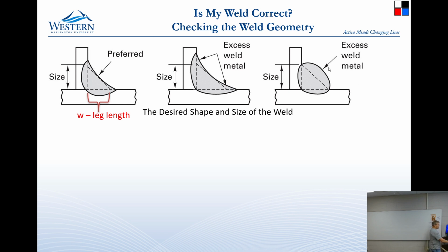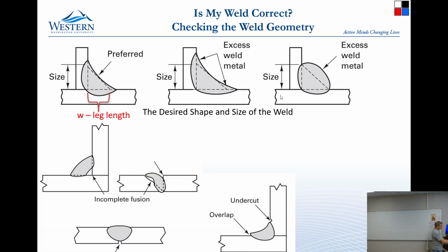If you happen to have excess weld material and it's bulging up like this, it leaves these sharp little notches on the ends. Those sharp little notches are nearly impossible to get paint into, but the water will pool in those, and then it will cause very rapid rusting, because it is down there in that heat affected zone that already has poor properties. And so that's a bad thing too. Anyway, lots of other ways to screw up welds.